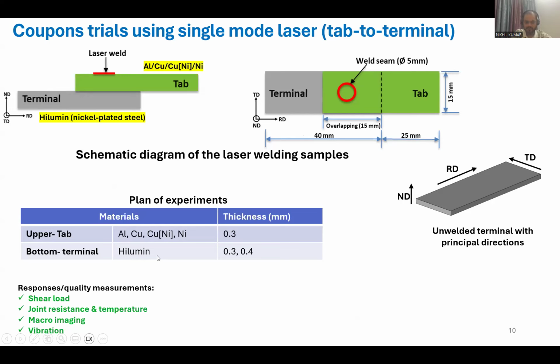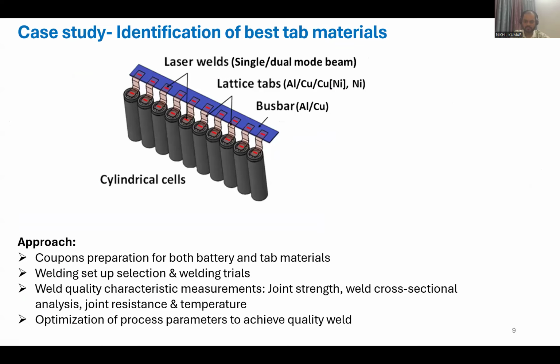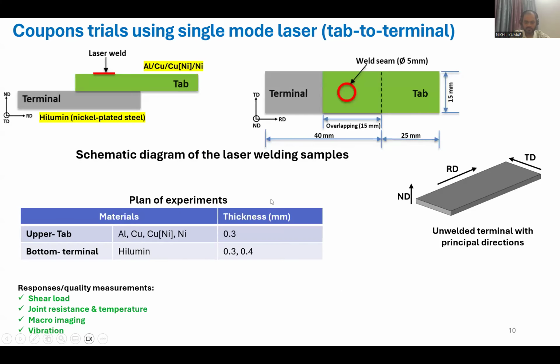The top material thickness is always 0.3, and for the bottom material I'm going to use 0.3 and 0.4, both one by one. Why 0.4? Because the cylindrical cell's positive side terminal thickness is 0.4, and the bottom side thickness is 0.3. So you have to optimize both sides, 0.4 and 0.3, for connecting the module.